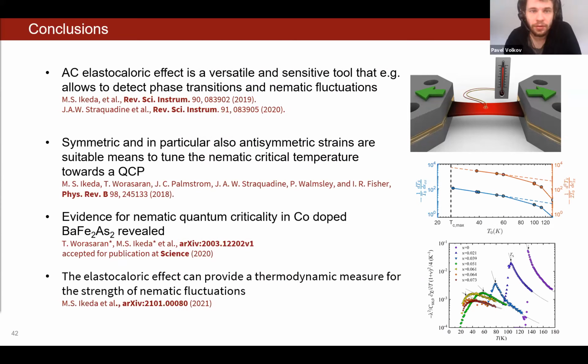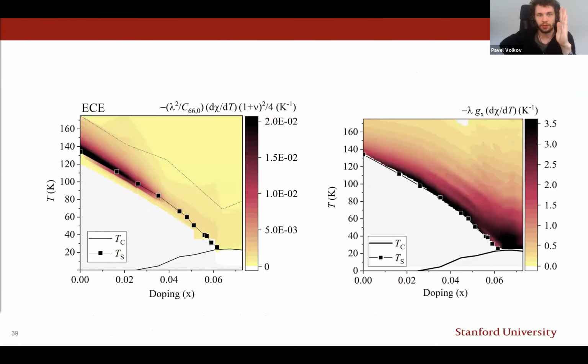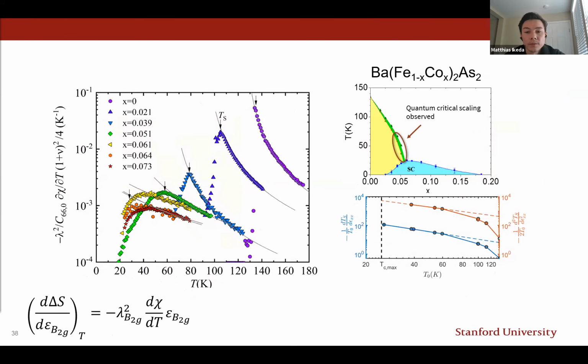So, is the Curie-Weiss temperature that you observe in elastocaloric measurements corresponding to the actual transition, or is it shifted from the actual transition? So it's again divergence against the bare transition. So it's basically T star, right? So it's not diverging towards TS, but towards the bare transition temperature T star. And in this case, the difference is due to the finite strain being applied, or can you elaborate on that?